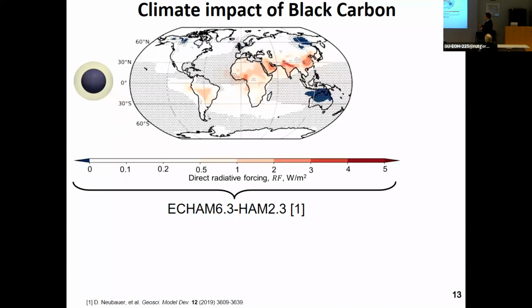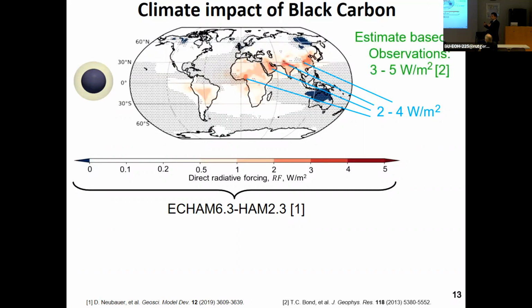But of course, you may have noticed already the red spots over here, which are areas that still have high emissions of black carbon that contribute to global warming. And in these areas, we have radiative forcing ranging between 2 to 4 watts per square meter. Of course, these hotspots were known already, but the predictions based on the observations that I showed you before suggested a radiative forcing ranging between 3 to 5 watts per square meter in these regions. So we have an underestimation of the radiative forcing by the current global climate models neglecting the black carbon morphology. So now, when we do the same simulations, but we use the new model for the black carbon structure,